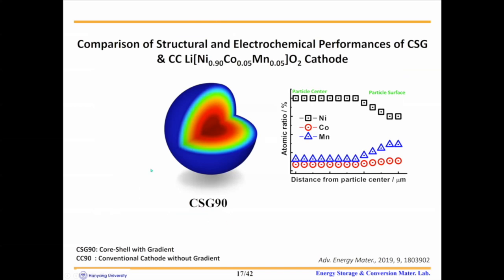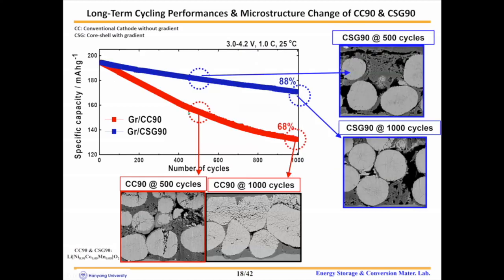This is another example of the concentric gradient. We prepared two NCM90 cathodes. One is the CSG90. The other is a conventional cathode without concentric gradient called the CC90. And then we compared the structural and the electrochemical performance of the two cathodes. As you can see from the long-term cycling performance, the CSG cell shows a much improved cycling performance with a capacity retention of 88% after 1,000 cycles compared to 68% for